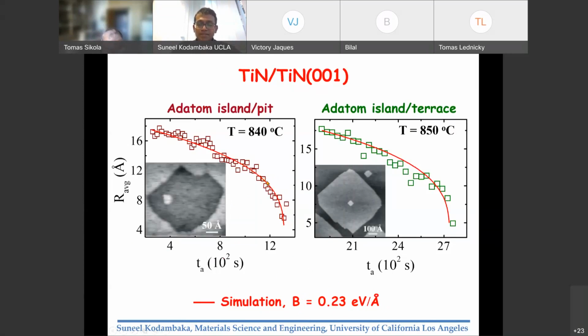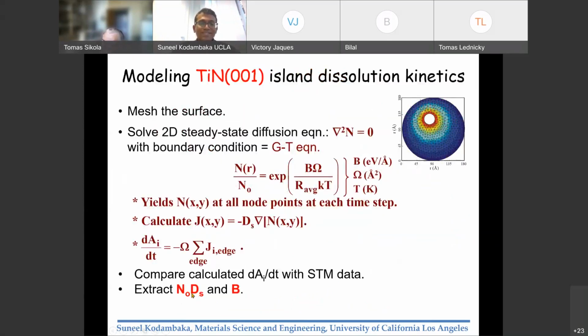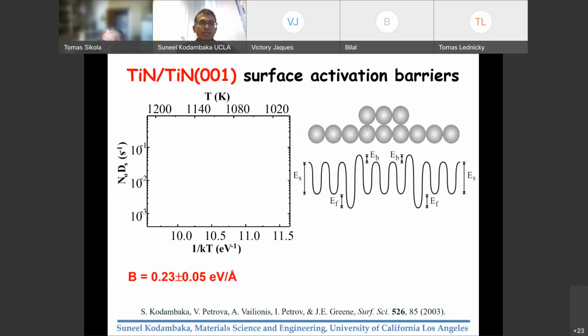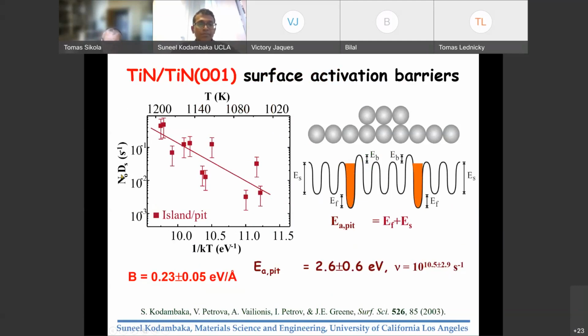From these types of fits, we can extract this parameter at each of the annealing temperatures. So we can now plot N sub 0, which is the equilibrium atom concentration, times the surface diffusivity for titanium nitride. This is the data obtained from these fits for different islands, as a function of the annealing temperature, and this is all done by STM. The slope of this curve is the activation energy, which corresponds to the energy required to remove an atom from an existing atom island. That's the atom formation energy, which corresponds to this N sub 0, plus the surface diffusion parameter, that's the E sub S. The total energy we get from this is about 2.6 electron volts.